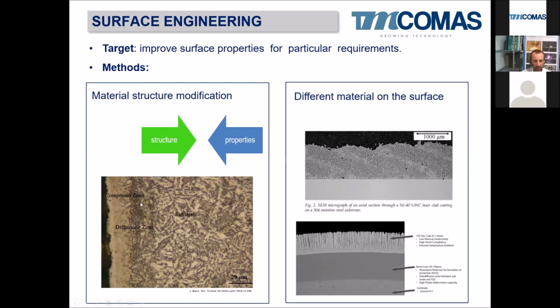And this example is a clear example of a diffusion surface treatment. Here on the left side of the picture, you can see that white coating, that white layer, is a diffuse layer, and then here is the base material, the substrate material, which has not been affected by this surface modification. So in this picture of a nitriding process, this is 20 microns, so about 20 microns of the surface has been modified.